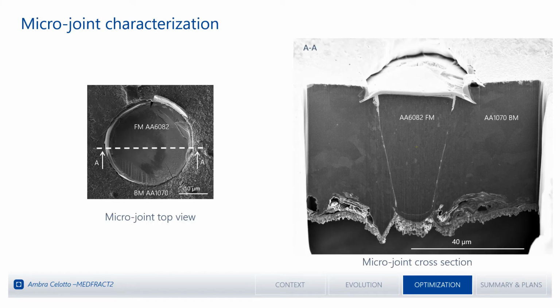Once more, by cross-sectioning the microjoint in its middle, we find ourselves in front of something that is quite similar to a conventional V-shaped butt joint, that in this case is just axisymmetric, in which the deformation of the grains, above all in the base metal, can tell us something about the flow of the metal while the welding was occurring.